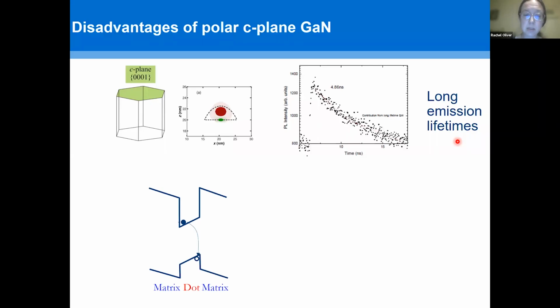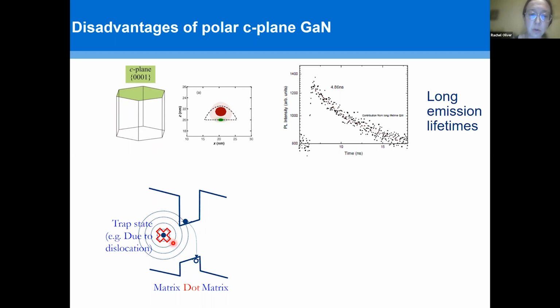It also has other consequences. We already have said that we have these internal electric fields. And here I'm modeling my quantum dot for simplicity just as if it were a quantum well. So these internal electric fields separate the electron and the hole. We also have a whole lot of defects in these materials, these dislocations due to heteroepitaxial growth. They create states in the band gap and charges get trapped at them. So there's a field associated with those charges. And that means we sum up the field associated with the charge and the internal field in the quantum well. And that gives a slightly different overall field in the quantum well, which gives a different wavelength of emission and a different intensity of emission.